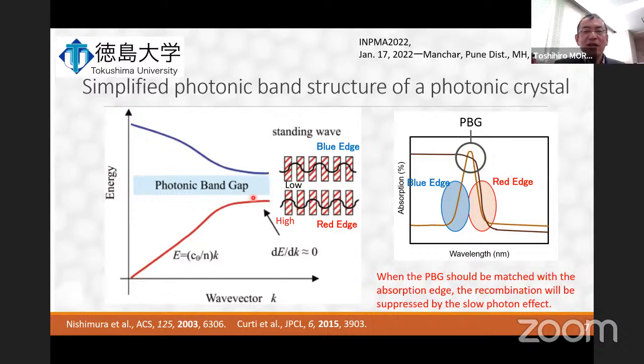The photonic band gap position appears at the minimum or maximum of the absorption spectrum, like this, associated with the red and blue edges at the longer and the shorter wavelength side of the maximum absorption peak. To suppress the electron-hole recombination, the absorption edge of the material shown here should match the red edge of the photonic band gap, since the electron will be localized at the high refractive index material. Electron in the material can move too hard to recombine with the hole in this case.